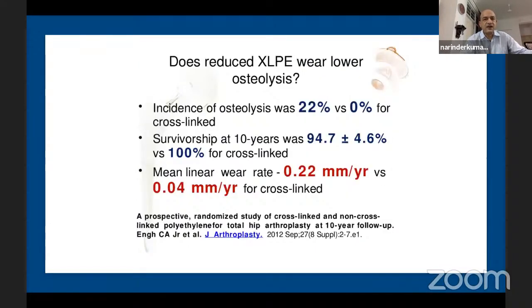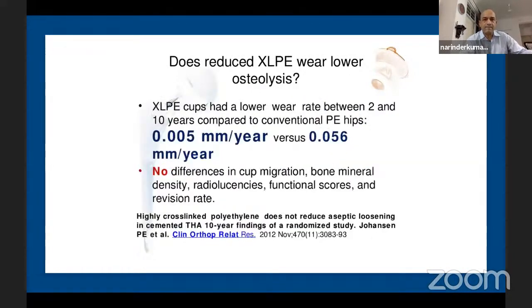But does this wear lead to decreased osteolysis also? Yes, it does. We have 10-year follow-ups, 15 years, and 20. Now 20-year follow-ups are also close to being available, which show that osteolysis is almost nil at 10 years in this study, but longer term studies have shown that osteolysis is much, much lesser.